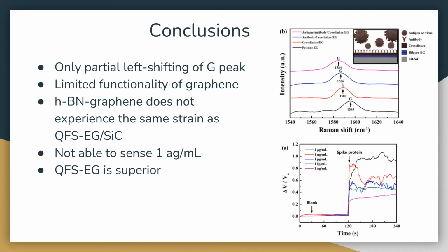So major takeaways. We found that there was only a partial left shifting of the G peak in the hexagonal boron nitride on graphene biosensors, as opposed to a complete left shifting that's seen in the quasi-freestanding epitaxial graphene biosensors. This points to a limited functionality of the graphene that's due to the fact that hexagonal boron nitride on graphene simply does not experience the same strain effects that are seen in quasi-freestanding epitaxial graphene with its silicon carbide substrate. Therefore, the hexagonal boron nitride on graphene biosensors are simply not able to sense the 1 attogram per ml of the COVID-19 spike protein. Therefore, we have proved that the quasi-freestanding epitaxial graphene biosensor is indeed superior.